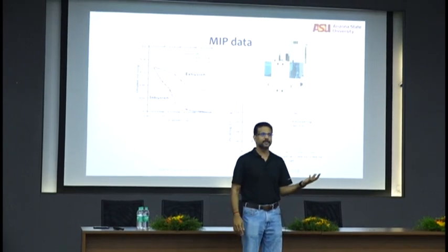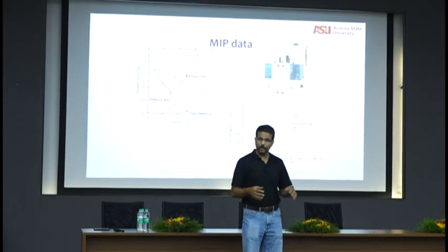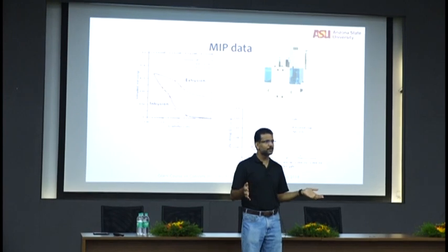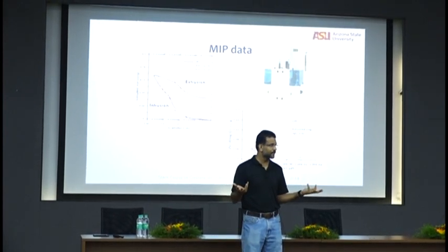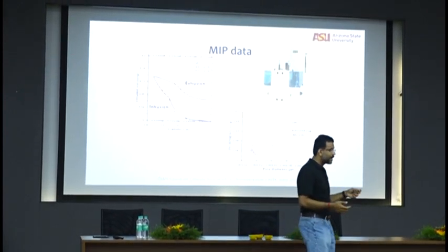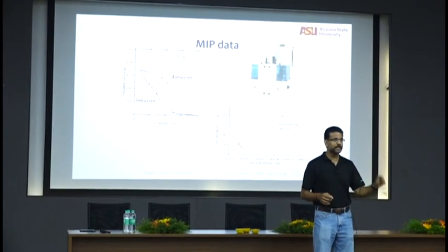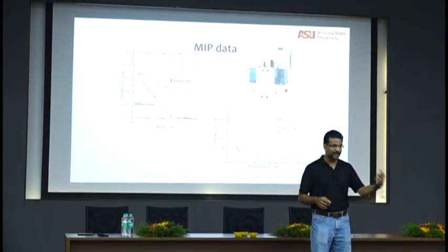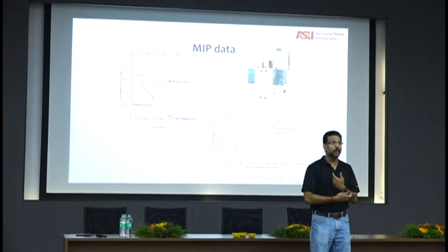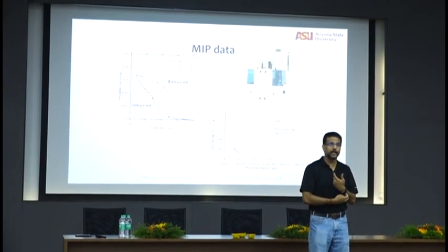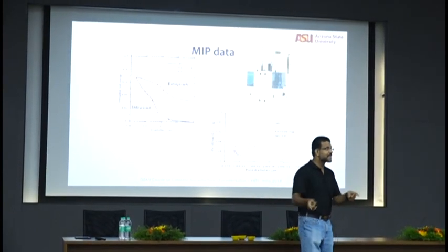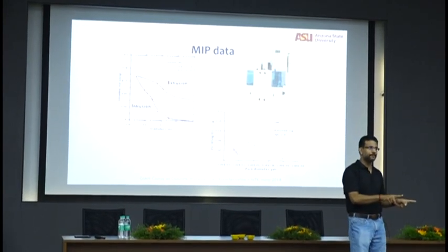Oh, I did microstructure. I took this wonderful picture. What are you using it for? I have no clue. Nobody gets any benefit from that, right? You look at the microstructure and say, well, I want to find out, am I producing enough CSH? Or do I have extra ettringite? I want to know the calcium silica ratio of it, so that I know if I have late-age durability problems. That's why you look at the microstructure.